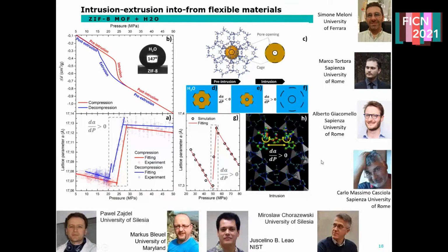As I mentioned before, some of the examples of intrusion-extrusion involve metal-organic frameworks. Those are fascinating materials because they provide certain properties which are not available for rigid materials like silica or zeolites. But at the same time, they provide a lot of challenges in terms of the mechanism of how the intrusion-extrusion happens. For example, as you can see in these images, the intrusion-extrusion into the ZIF-8 metal-organic framework qualitatively looks similar to the intrusion-extrusion into rigid materials like silica.